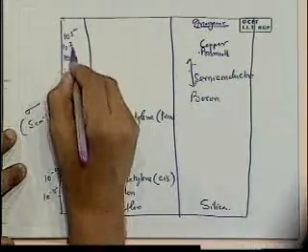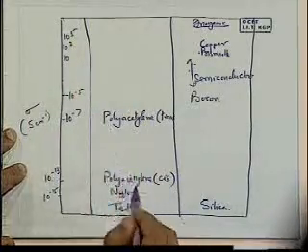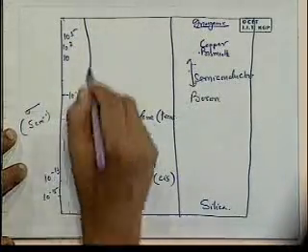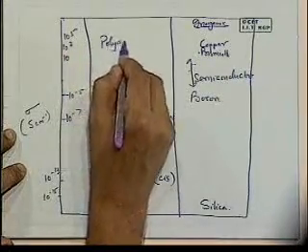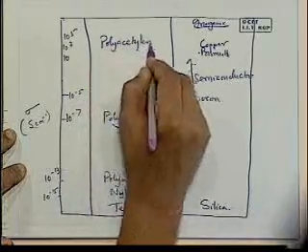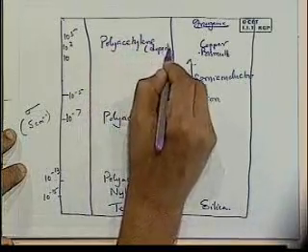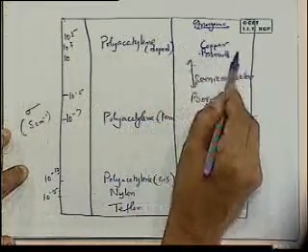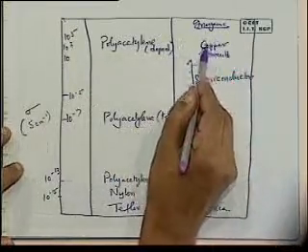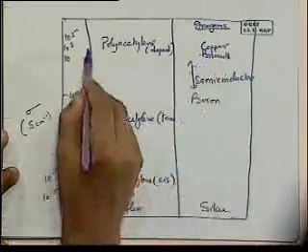It's interesting that doped polyacetylene, this is undoped, doped polyacetylene has been found to have as high as this range. So what do we see? It's behaving like a metal practically. The corresponding inorganic side, we're talking of conductivities somewhere near copper.